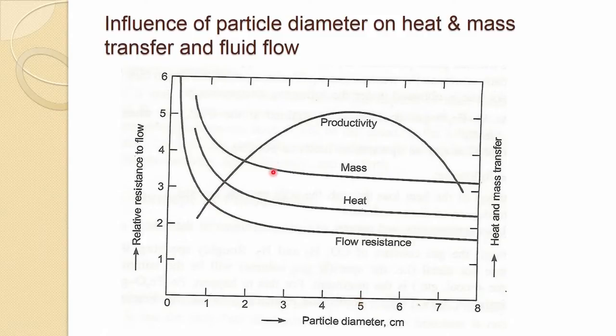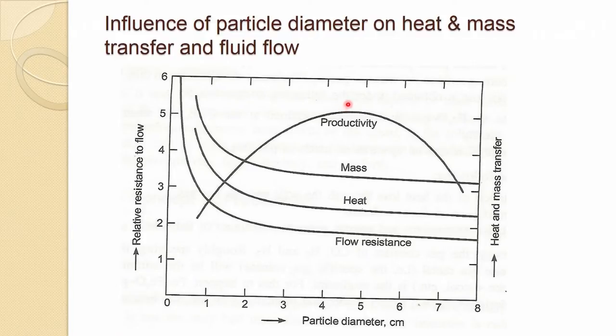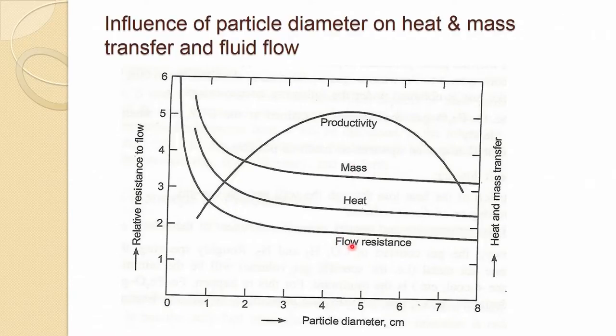Avoiding minus-10mm particles and moving toward slightly larger sizes is preferred. Productivity reaches a maximum when particle size is about 45 mm (4.5 cm) — at that point the highest productivity is achieved, allowing more blast to be blown. This shows how particle size affects mass transfer, heat transfer, and fluid flow together.